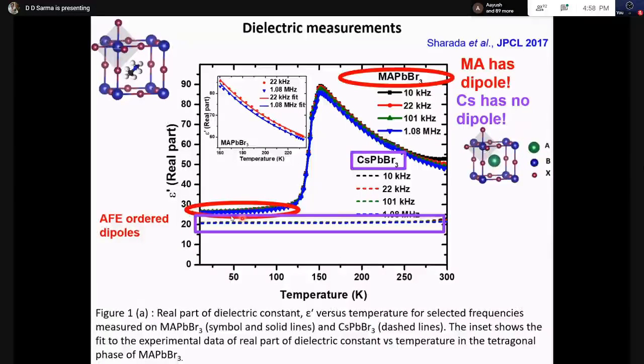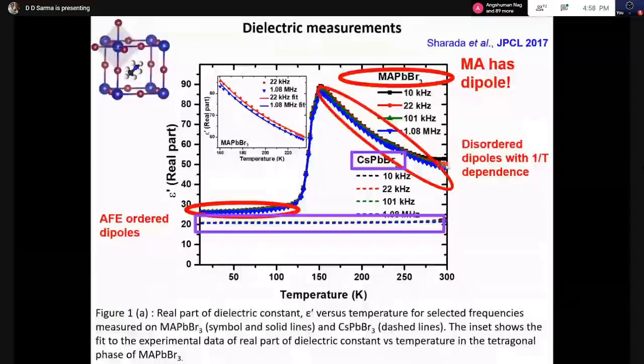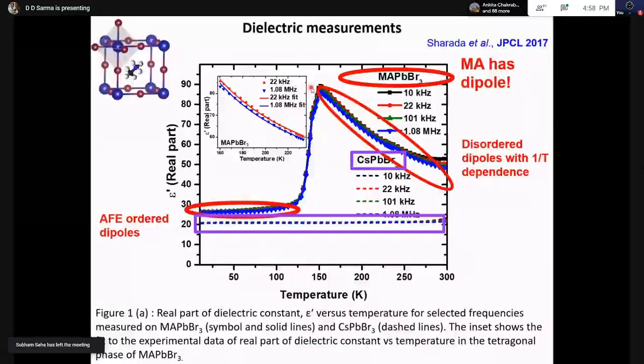At the low temperature, where I know there is an antiferroelectric ordering such that dipoles don't per se contribute to the dielectric constant, you can see it looks more or less like the CsPbBr3. And that is because the dipoles are not contributing. But look at this part. There's a huge dielectric constant, and not only that, it is increasing as 1 over T. As I lower the temperature, it is going up, just like a free dipole should be.